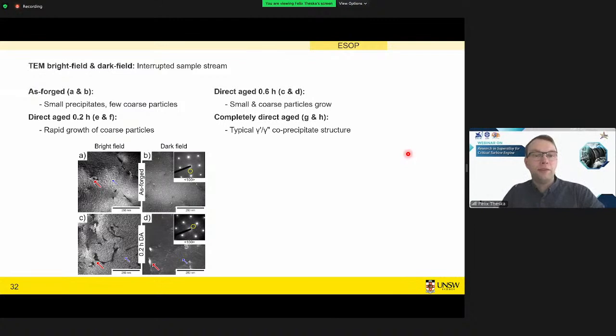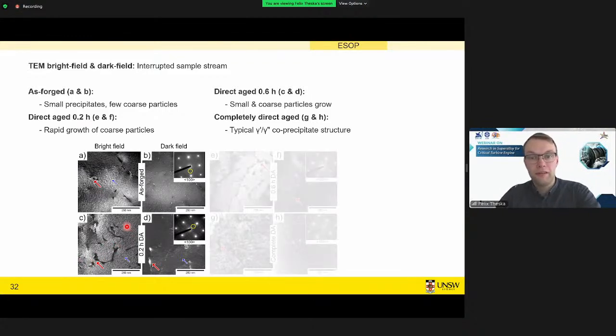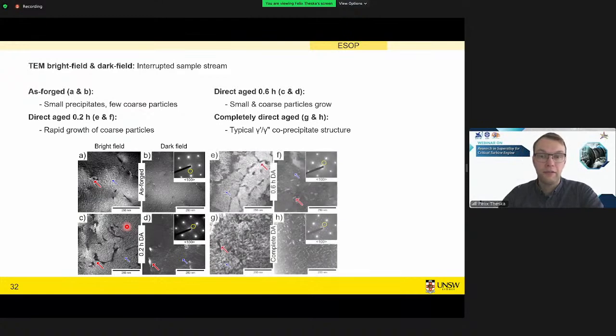Then we can take these samples into the TEM, and if we look at the as-forged material, that's figures A and B, we see there's a lot of small precipitates and a few larger ones. Now that's not unexpected because the material has been air-cooled, so there might already be some particles forming during the cooling process. After 0.2 hours direct aging, these small precipitates haven't changed that much, but we do see that these larger structures grow quite quickly. After 0.6 hours aging, we find that these larger structures have grown a lot, but also the smaller particles now start to grow. So that after the full aging in figures G and H, you have this typical microstructure of these really densely arranged precipitates.